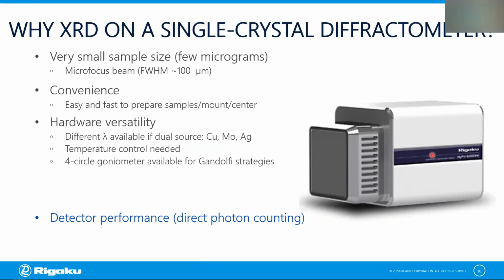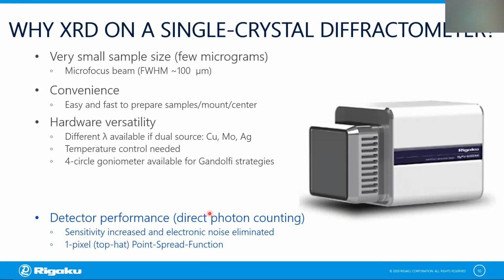The detector is a HyPix 6000 HE. And again, this is a direct photon counting detector. That means that it counts each photon that hits it and then discards it, instead of integrating all the photons that hit a given pixel throughout an exposure. That has 2 consequences of interest to us. First, that direct photon counting technology increases the sensitivity of the detector while virtually eliminating almost all electronic noise. And the second consequence is that the point spread function for that detector is basically one single pixel. That means that all the photons that hit a given pixel will remain imprisoned on that pixel, instead of leaking across neighboring pixels, which is what happens with CCD and CMOS detectors.